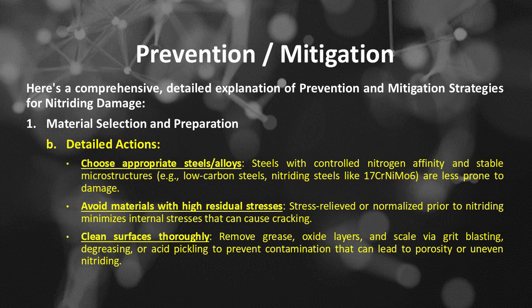Nitriding steels like 17CrNiMo6 are less prone to damage. Avoid materials with high residual stresses. Stress relieving or normalizing prior to nitriding minimizes internal stresses that can cause cracking. Clean surfaces thoroughly, and remove grease, oxide layers, and scale via grit blasting, degreasing, or acid pickling to prevent contamination that can lead to porosity or uneven nitriding.